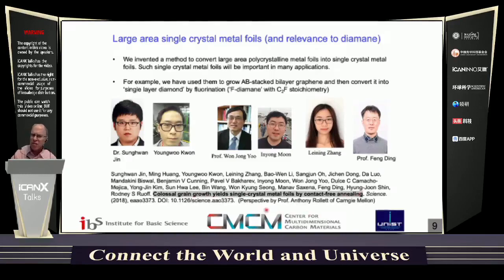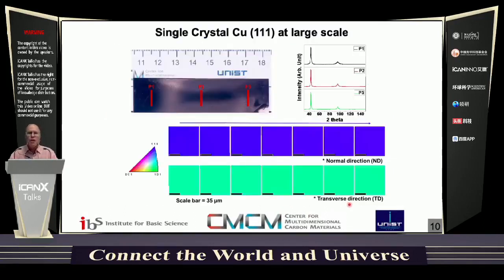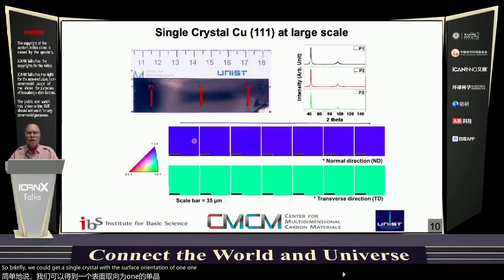There's a very nice perspective on our article by metallurgist Anthony Rollett. So I'm sorry about the spelling here. That should be Carnegie Mellon. So briefly, we could get a single crystal with the surface orientation of 111, as shown in these electron backscattered diffraction, EBSD, images. And the in-plane orientation is also everywhere identical. So it's a true single crystal over a very large area.